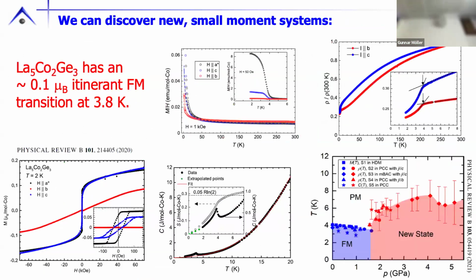We can also just try to discover our own new small moment systems. La3Co2Ge3 is a crystal structure we discovered. It would be a nightmare with a moment-bearing rare earth because there are multiple rare earth sites, but with a silent 4f shell with lanthanum, we can just study what's going on with the cobalt, and we find a beautiful example of tiny, again, 0.1 Bohr magneton, itinerant ferromagnetism at 3.8 Kelvin. And what's lovely is it shows up in the specific heat. It shows up beautifully in the resistivity. We can see the ferromagnetism here.